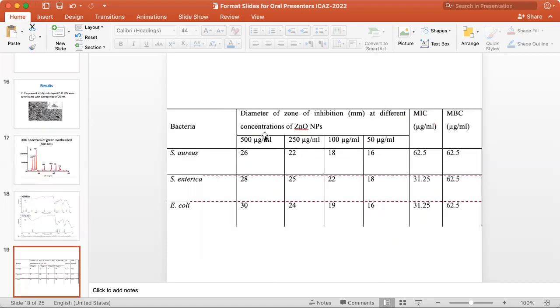Then in this table, you can see the in vitro susceptibility testing results. MIC values and MBC values have been shown. In case of zinc oxide nanoparticles, MIC values range between 31.25 to 62.5 microgram per ml, whereas MBC against all three tested bacteria was 62.5 microgram per ml.